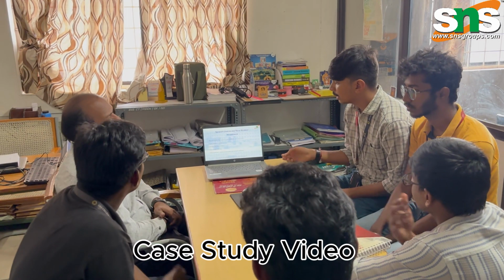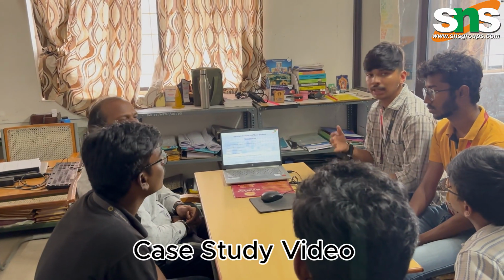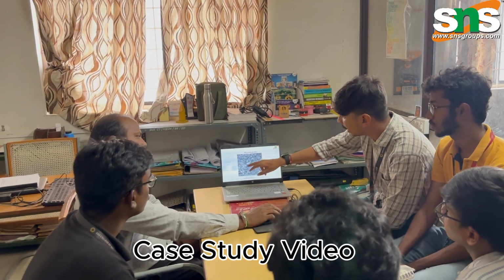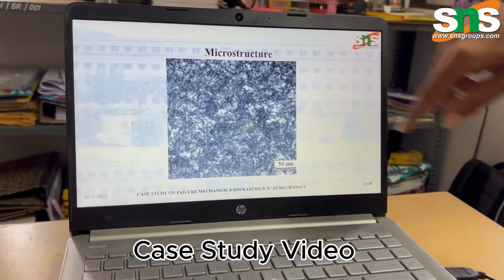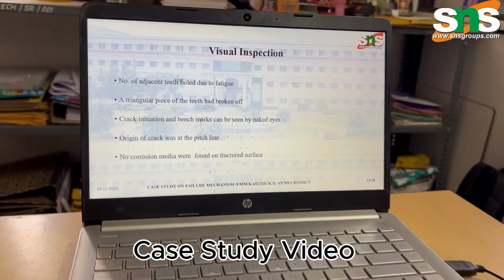The core hardness is 439 HV and the surface hardness is 550 HV. The core hardness is low because the material is surface hardened here. The case depth is 0.63 mm, and the microstructure consists of martensite and retained austenite. Here, the white color which we can see in the microstructure is retained austenite, and the black side is the martensite.